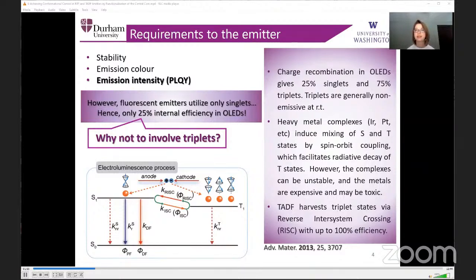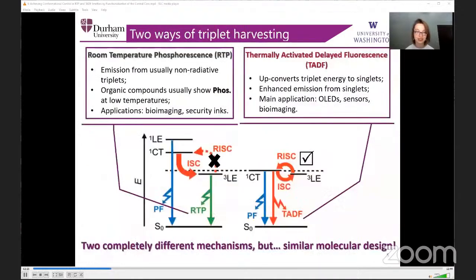Charge recombination in organic light-emitting diodes gives 25% of singlets and 75% of triplets. Triplets are generally non-emissive at room temperature. The utilization of heavy metals such as iridium and platinum induces mixing of singlet and triplet states by spin-orbit coupling. However, this kind of complexes tend to be unstable and the metals are expensive and toxic. In turn, TADF tends to harvest triplet states by reverse intersystem crossing, thus leading to 100% efficiency. Currently, there are two ways of triplet harvesting at the peak of research. This is room temperature phosphorescence and thermally activated delayed fluorescence. TADF upconverts triplet energy to singlets, thus leading to enhanced emission from singlet states.